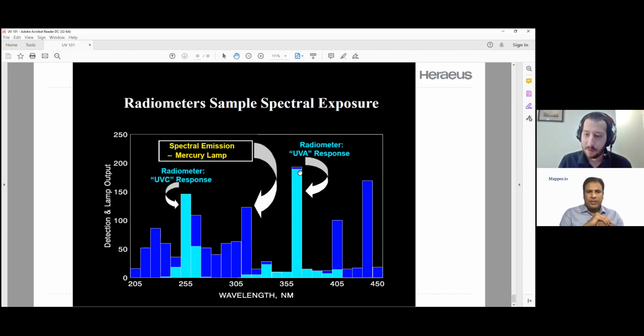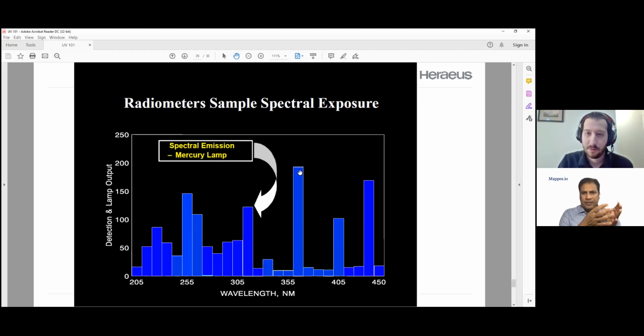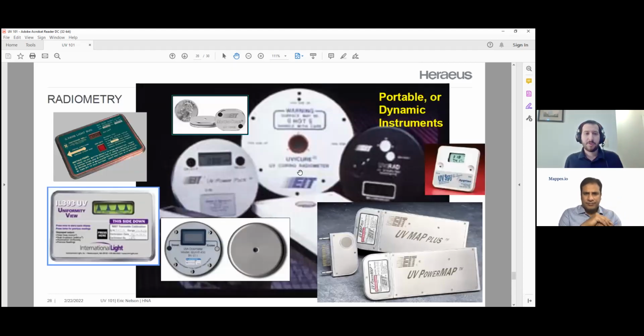Got it. So what kind of readings do you get? You get a UVA reading, you get a UVB reading? Yeah, so there's many different designs of radiometers. And typically the two things that they're measuring are peak irradiance, which is the highest energy level that the part or the radiometer is going to be exposed to, and total energy or total exposure. Total energy would be the summation of all the energy that the radiometer experiences when moving under the lamp. And typically, these two variables, peak irradiance and total exposure, are going to be measured at a single specific wavelength or wavelength band.